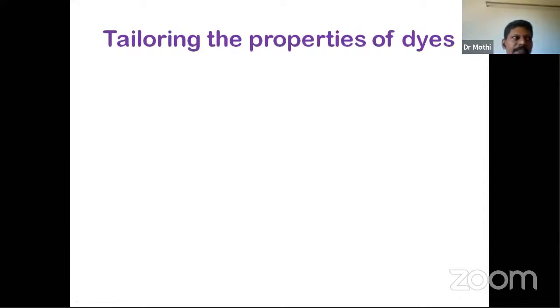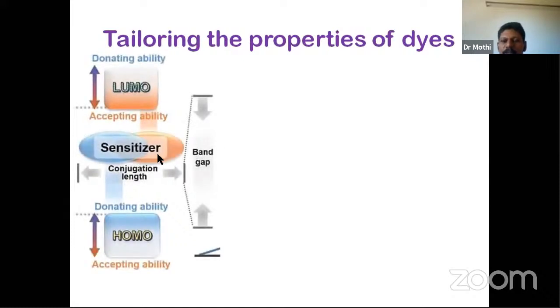Right. Now, this brings us to an important point where we can tailor the properties of the dye. How can we tailor the properties of the dye? So the dye molecule is basically an organic molecule. We can attach different groups. So there is always a possibility to attach different groups. So here I have shown the sensitizer. We can see in the bottom the conjugation length. So if we can increase the conjugation length, the double bonds, the triple bonds that are present in the dye molecule, then we can change the band gap of this dye.